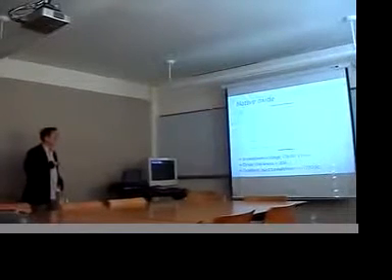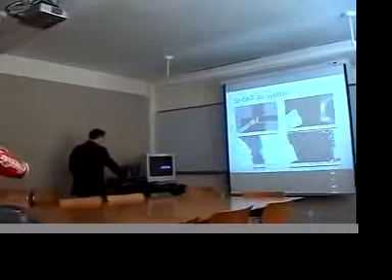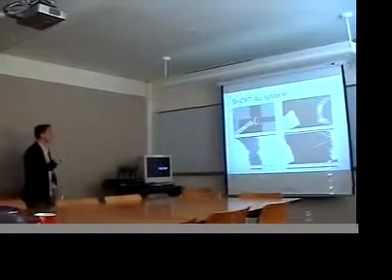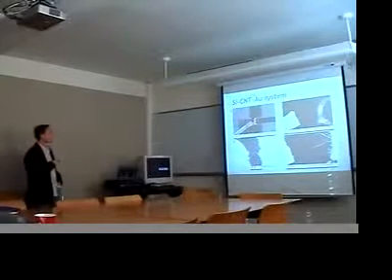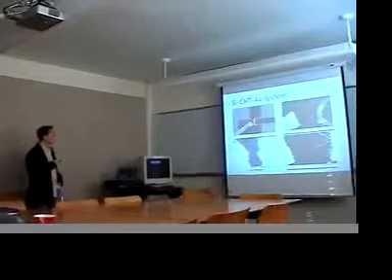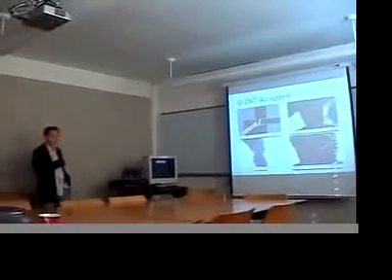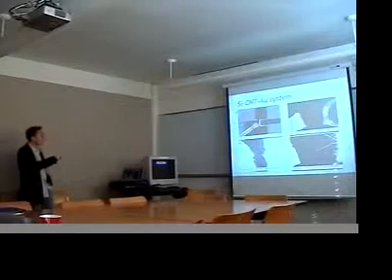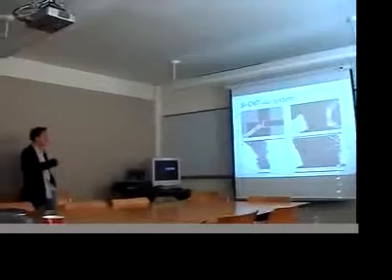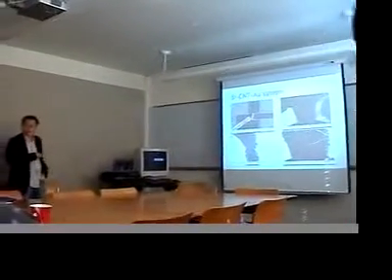So I think we took a long time to realize that maybe native oxide does matter in this case. And so we also did some work to try to get around this issue of native oxide by replacing the other side with gold. Basically, with brute force, we took away the heater, and Takeshi, with his manual skill, used the wire bonding machine to put down the gold electrode, and we did the normal process, and as you can see, there is some carbon nanotube connection between the two.